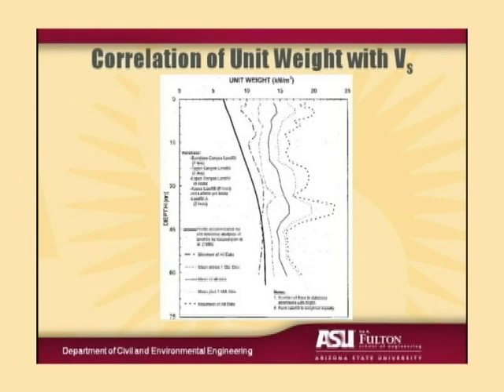In fact, working with Professor Stokoe, we correlated the shear wave velocity to the unit weight. We got a pretty good correlation. We used that correlation to take our shear wave velocity profiles and translate them into a unit weight profile for the landfill. The dark squiggly line is the median value. Here we're also showing the mean plus one standard deviation, the mean minus one standard deviation, and then the absolute maximums and minimums based upon this correlation.